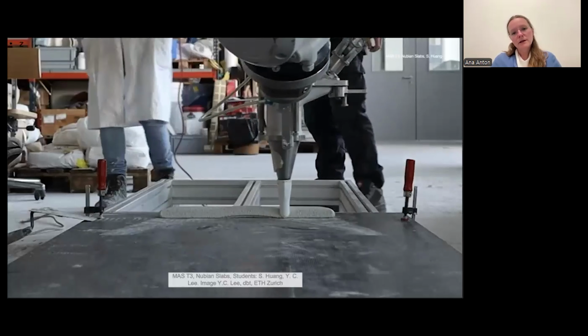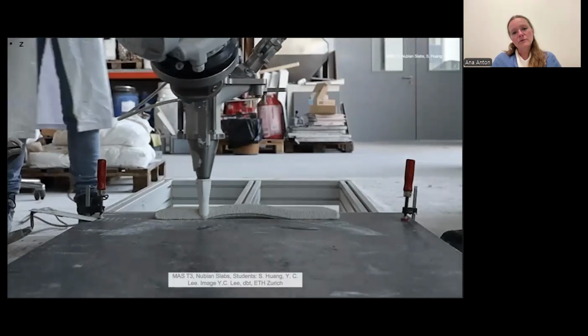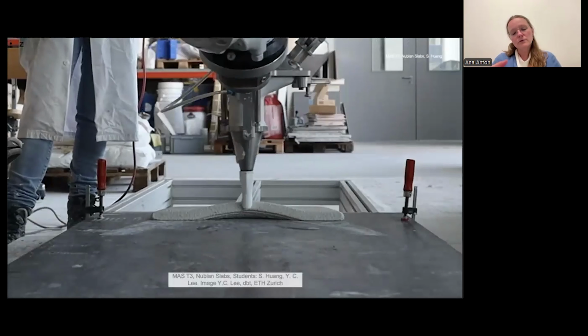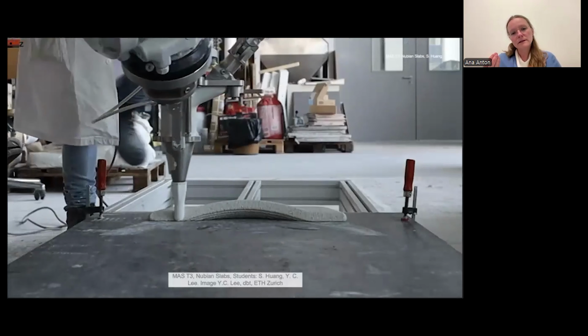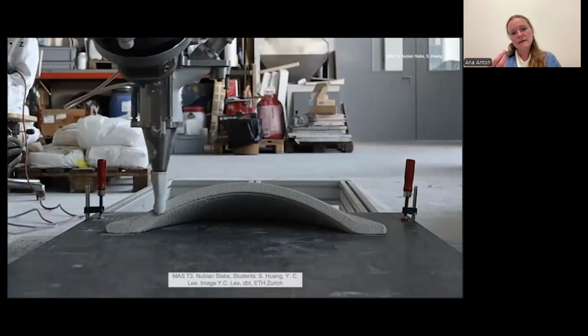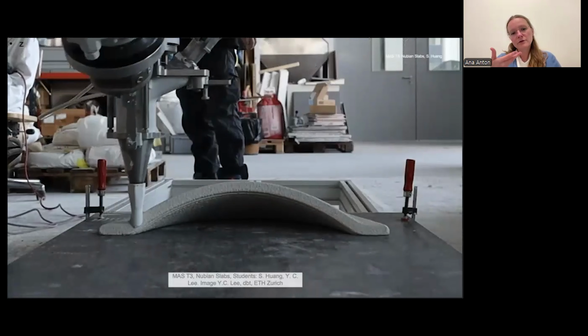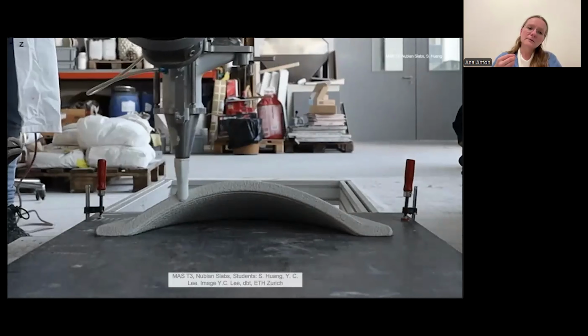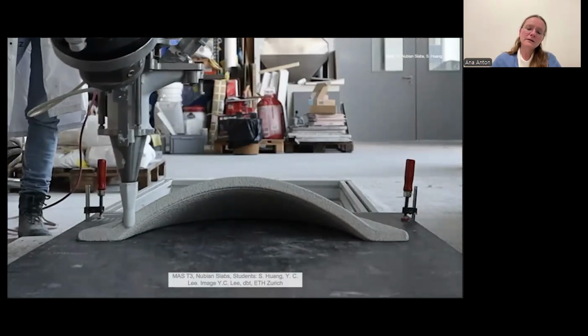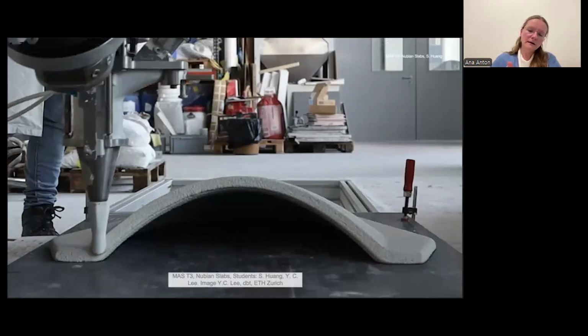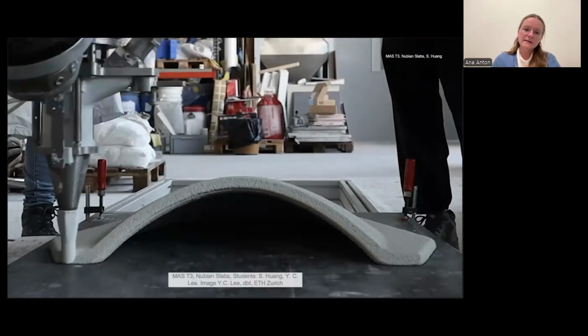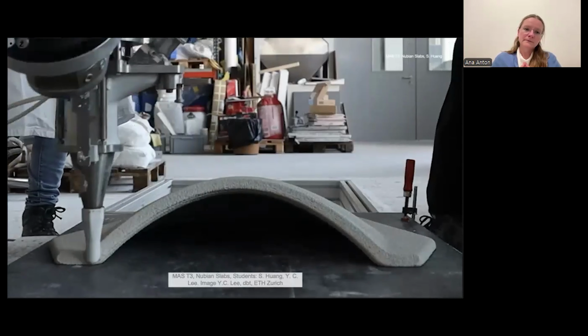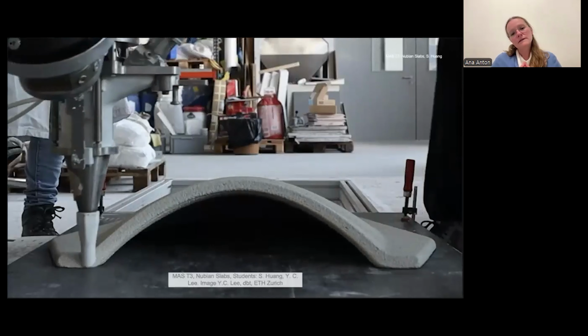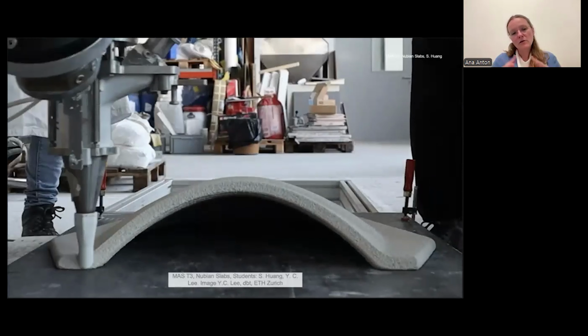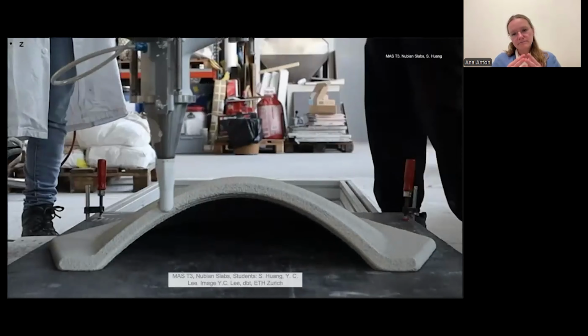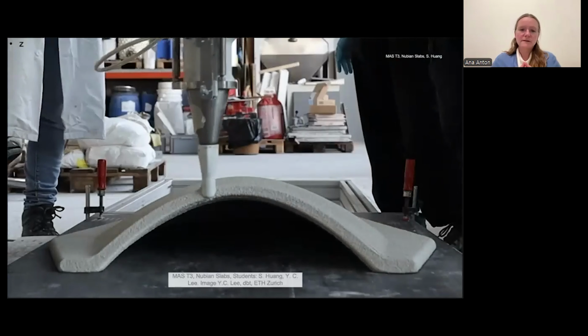We got our inspiration from those geometries because we could control the material in such a way that it could hold its shape only by the friction to the previous layers. So we actually put the layers of materials deposited in midair to replicate the bricks into a Nubian vault. So you can see that we can achieve this printing in midair almost only by creating funicular geometries that are